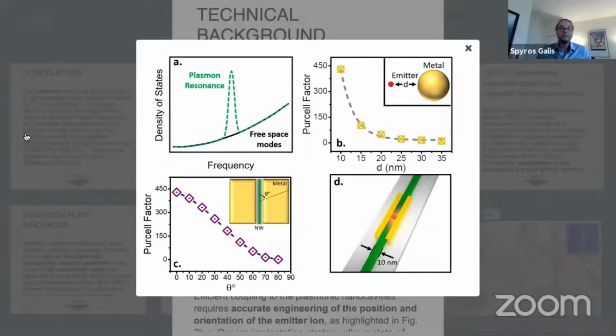So how are we planning to tackle these two challenges? For one, the nanometer scale proximity between the emitter and the cavity can be met due to the ultra-thin dimensionality of the proposed nanowires, which is less than 10 nanometer. And this is well within our reach of nanofabrication strategies. Now, as far as the orientation is concerned, we can take advantage of the anisotropic dimensionality of our nanowires, where the width of the nanowires is much smaller with respect to the emission wavelength of erbium ions, 1540 nanometer again, and that results in an anisotropic absorption and emission behavior for the erbium ions.